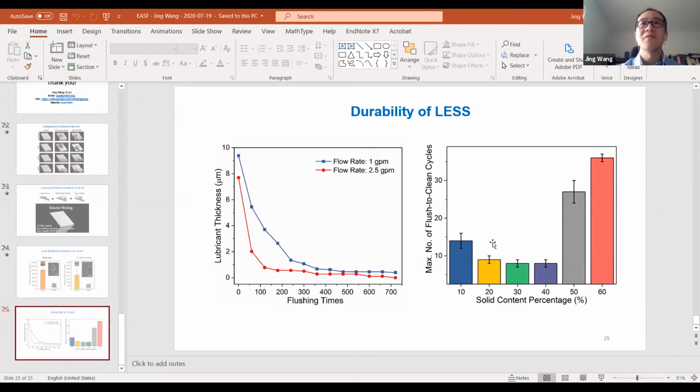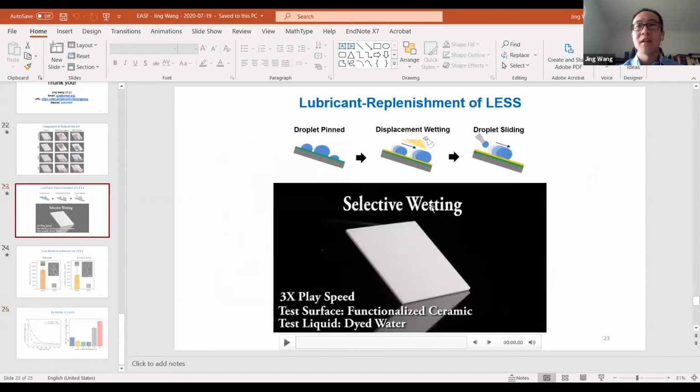So basically, if it is used very intensively, you have to apply the lubricants each week or every other day in a household setting. And also to be mentioned, the first layer of the PDMS grafting is permanent, so it's covalent bonding. Only the second layer is a functioning and also a sacrificial layer. So we can always reapply it.